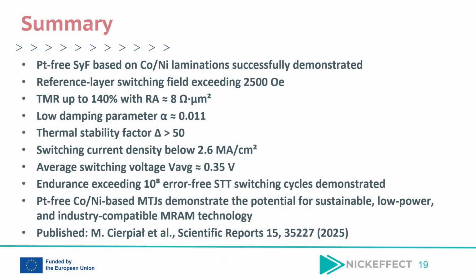The fabricated nanopillar devices also demonstrated efficient STT switching with switching current densities below 2.6 megaamps per centimeter squared and average switching voltages around 0.35 volt. In addition, reliable device operation was confirmed through endurance measurements exceeding 10 to the power of 8 error-free switching cycles. These results demonstrate that the PT-free cobalt-nickel-based MTJs can provide high performance, low power, and thermally stable MRAM devices while reducing dependence on critical platinum group metals. The presented technology therefore represents a promising route towards sustainable, energy-efficient, and industrial-compatible next-generation MRAM solutions for future AI and data-centric applications. The presented results were published in Scientific Reports in 2025.